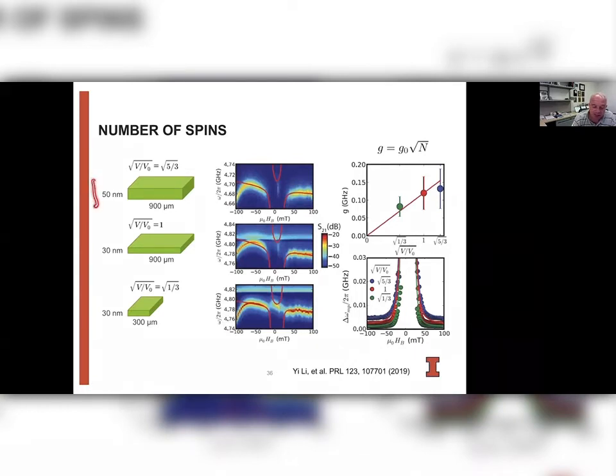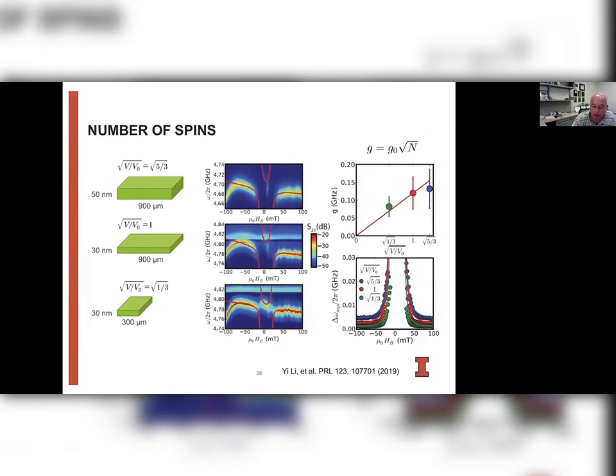Now, similarly, we can look at what is the role of the volume of the system. We can either make the system thicker, or we make the lateral dimension smaller, and in both cases we can change the volume by a factor of about 3. And what we see is that when we do this for the larger volume, we get the larger coupling. For the smaller volume, we get the smaller coupling. And it's more or less linear with the square root of the volume, as we would expect. So again, this confirms our picture about the strong coupling in the system.